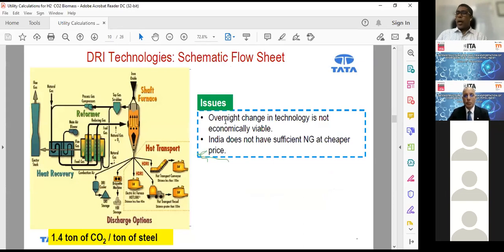And of course, there are other ways of making iron, that is DRI technology, which is available commercially. Here the coke is not used for making iron, but natural gas is used. And the carbon dioxide emission is also less, about 1.4 ton of CO2 per ton of crude steel. But there is a problem because this process requires natural gas.